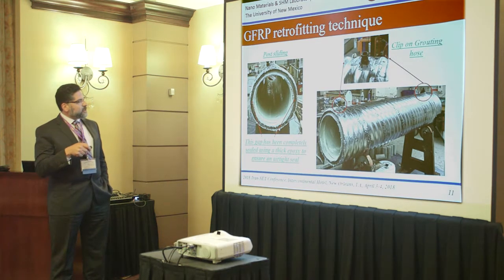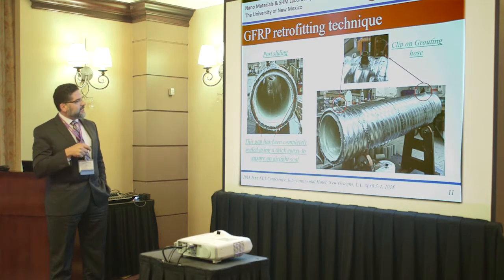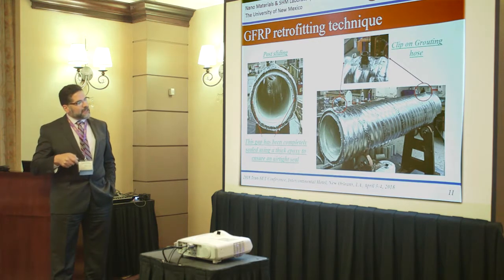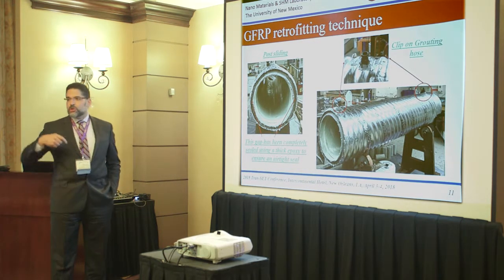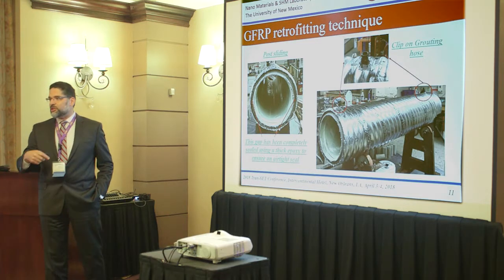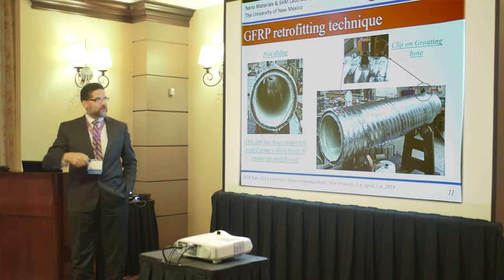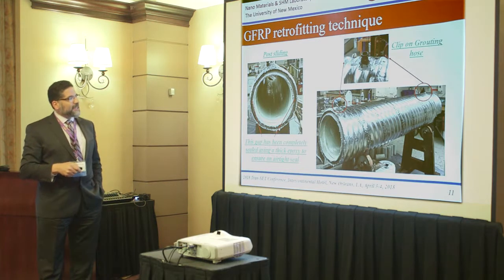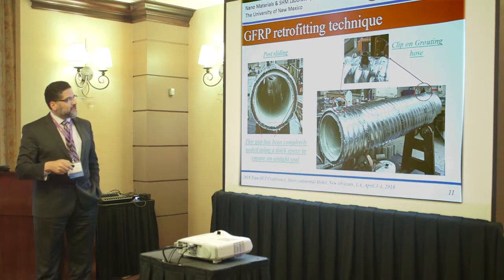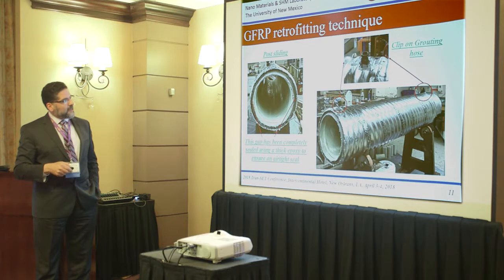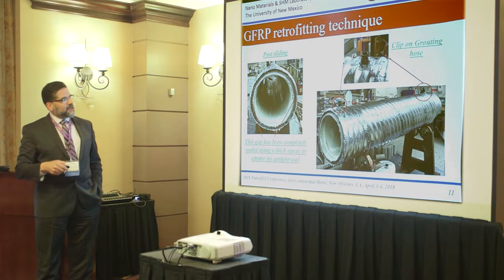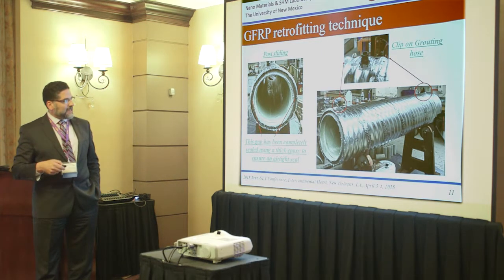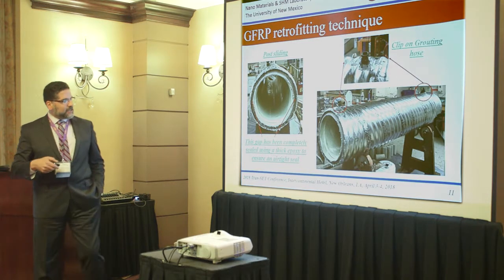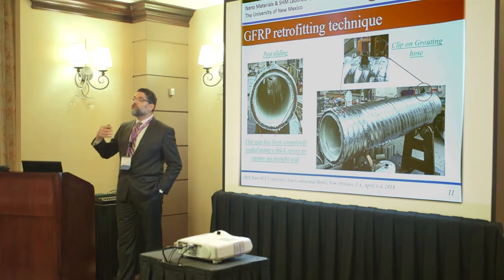The next step for doing our test, our simulation, is we actually went at the end, post-drilling, and we put a thick epoxy layer at the end. That could be another, say a wood section at the end, which you would need to do at the exact culvert so that you limit the place where you are going to have the grout. On the pipe itself, again, that will be part of the design of the real project. We have a hose connected to the pipe here and here, which will also need to be designed in the field when this is field applied, so that you can pump the polymer concrete on one side and get it on the other side, so that you make sure you fill all the gap.